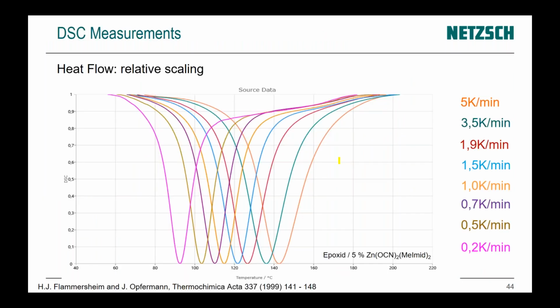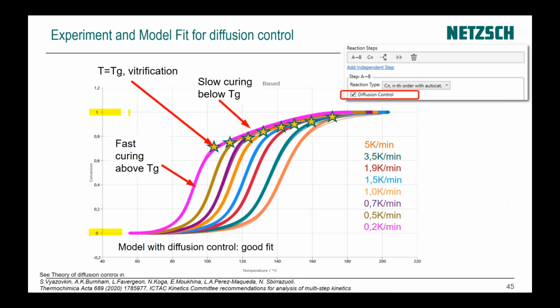Here is an example. We have different heating rates from 0.5 to 5K per minute. We can recalculate everything to degree of conversion from 0 to 1, and we see that everywhere the reaction goes fast until some point, and after this point the reaction goes slow. For 5K per minute the reaction goes fast almost until the end; for 0.5 or 0.2K per minute this change happens very early.